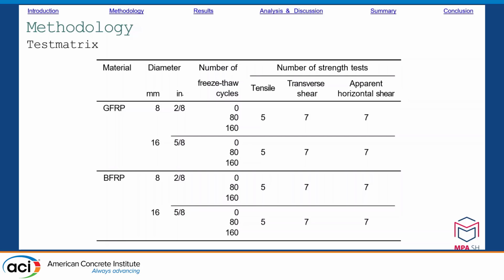The bars were divided into 3 test groups. The first group was not exposed to any freeze-thaw load. The other 2 test groups were placed in a water bath for a period of 11 weeks to allow saturation of any pores and defects. They were then placed in the freezer for 80 and 160 freeze-thaw cycles respectively. 3 different tests were carried out on the bars after the freeze-thaw cycles to obtain results on the material properties. Tensile tests, as well as tests on transverse shear strength and horizontal shear strength, were carried out, which are presented in more detail below.